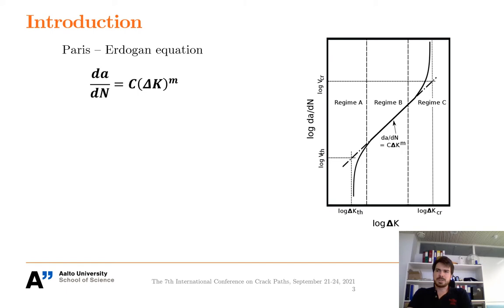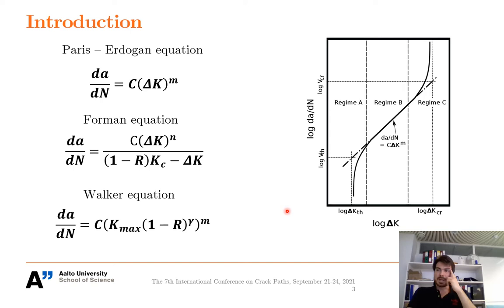The apparent self-similarity of this expression may be misleading as a variety of more complex variants has been proposed usually in terms of delta K or R. For instance, Forman equation or Walker equation. The two main reasons for this complexity are history or memory effect arising from the crack closure and the fact that a fracture process zone encodes the extent of plastic deformation due to the peak stress during the fatigue process. Our work concentrates on the stochastic nature of fatigue crack growth. We investigate the dynamics of time scales shorter than on which self-similarity growth laws are formulated. This itself presents an outlook on fatigue fracture as a stochastic phenomenon with fluctuations.